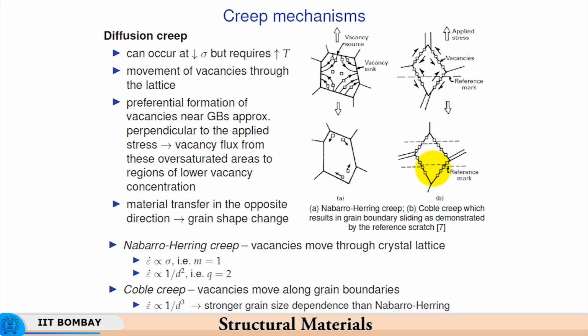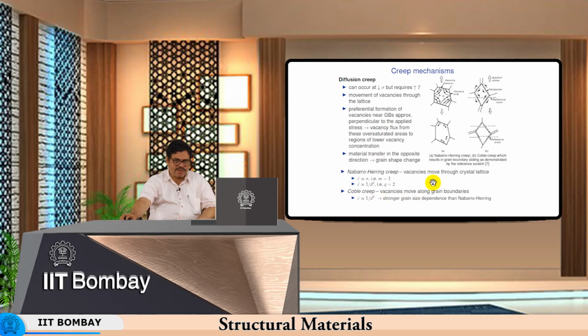Now, the next stage is what is called superplasticity, where you have only grain boundary sliding, practically 100% grain boundary sliding. There is no dislocation activity at all, and that is where you need extremely fine grain size, extremely small grain boundary paths, so that the viscous effects are the ones which dominate the resistance to deformation, and any scratch or any damage gets evened out. So, there is absolutely no effect of inhomogeneous strain rate. The strain rate sensitivity is equal to 1 practically. So, that is the effect of grain boundary sliding. As the temperature continues to increase, the grain boundaries become increasingly viscous. So, we have the same thing which we had seen earlier.